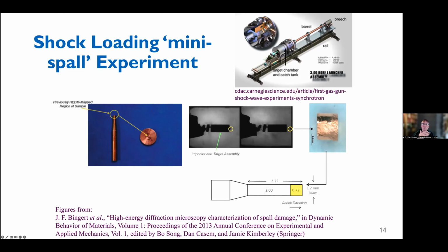And the miracle in this was that we had the millimeter cubed, we measured it at 1 ID, we sent it back to Los Alamos, they did the experiment, and then poor old John Bingert had to scramble around the chamber and somehow go find this little tiny piece of copper, which he did, and send it back to us in time for the scheduled beam time. But it worked. It all happened.